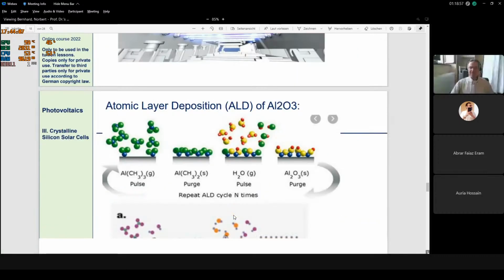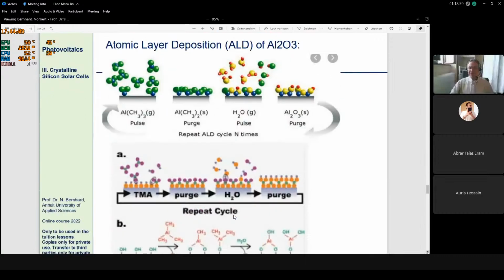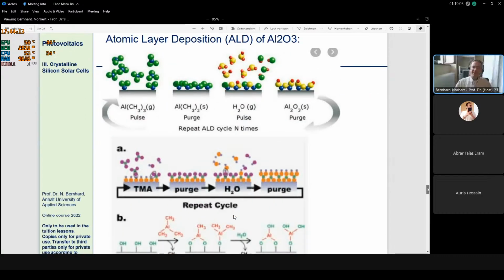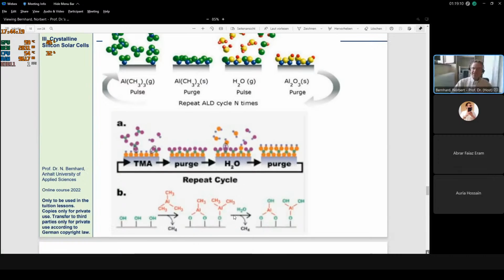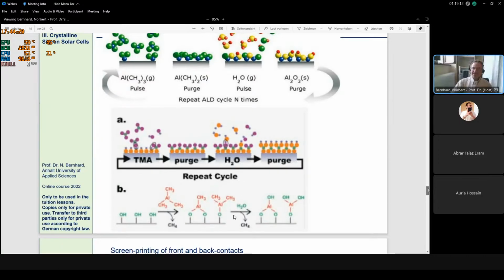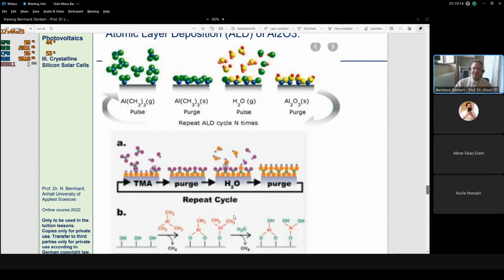I said already on the back side, we have this double layer of aluminum oxide and silicon nitride. And the aluminum oxide layer is usually deposited by another process, which is called atomic layer deposition. Atomic layer deposition works in a sequence with alternating pulses and purges.